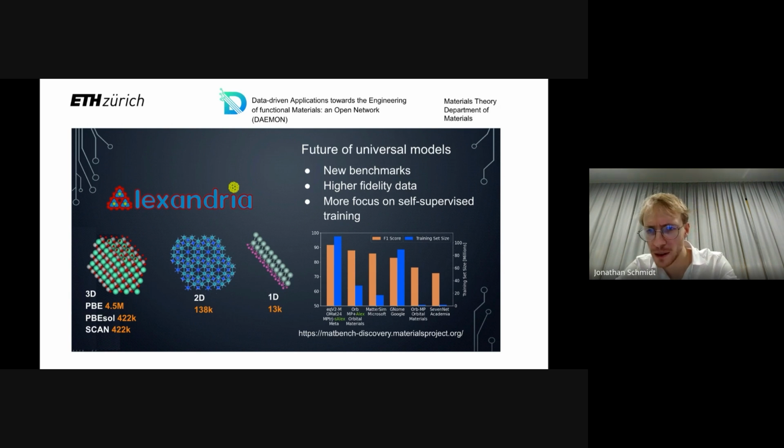So yes, for each crystal structure that we calculate, we directly predict the distance to the convex hull, and then if the material is close to stability, we calculate the phase diagram in the concept of the convex hull, based on all the structures in our database that are stable.